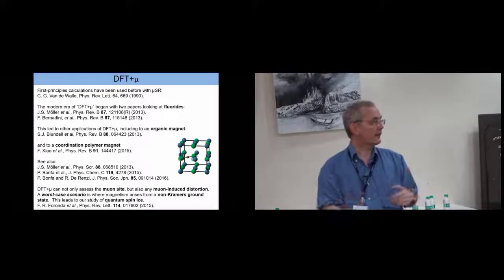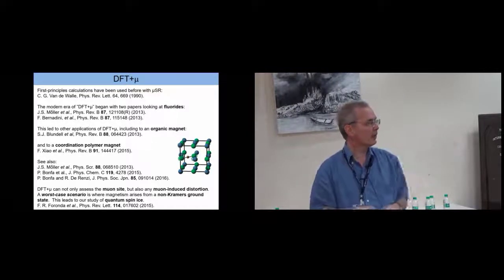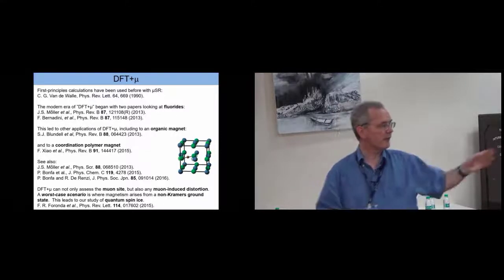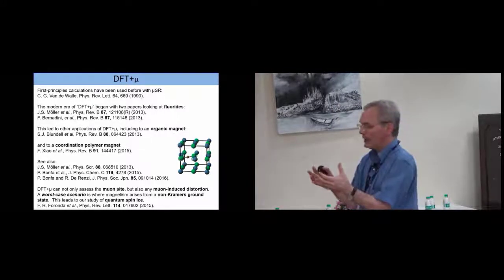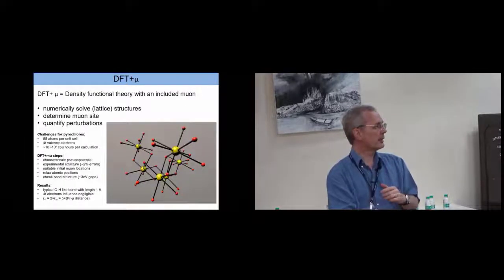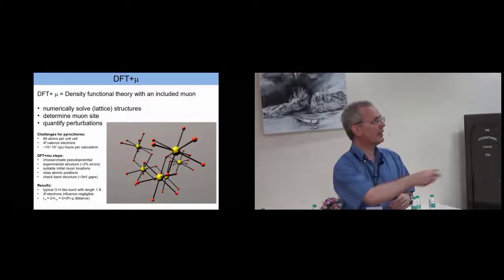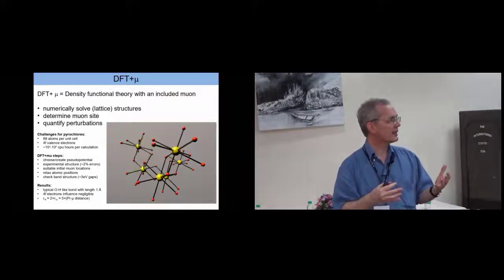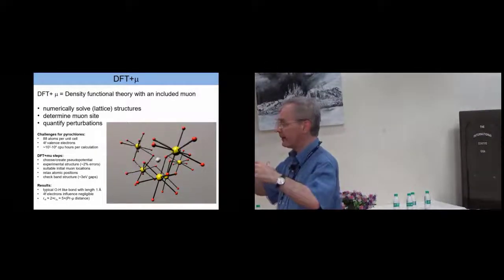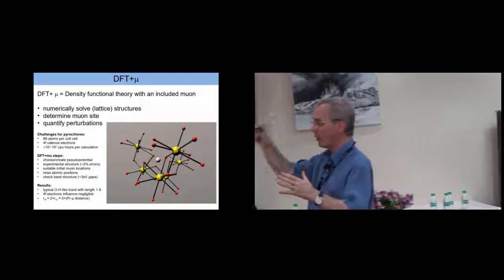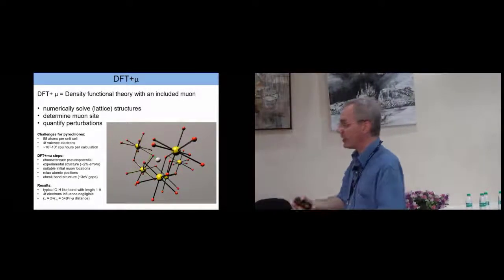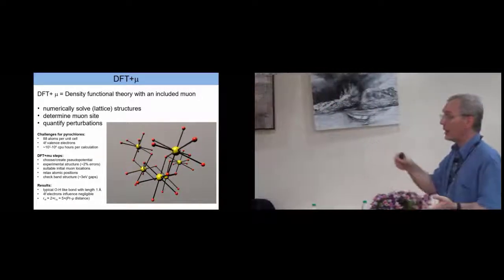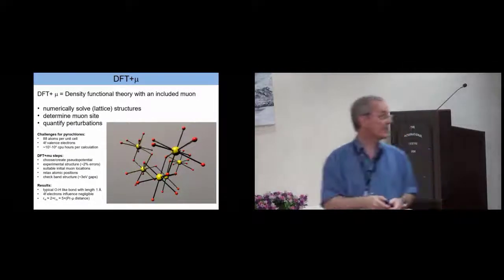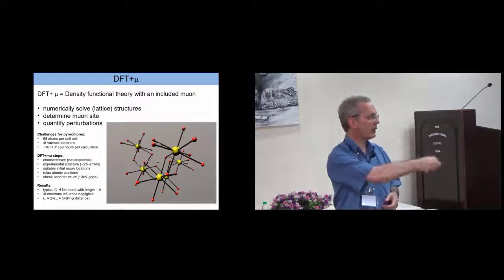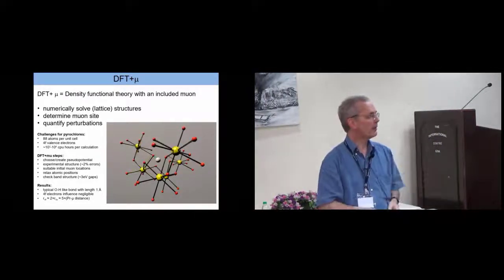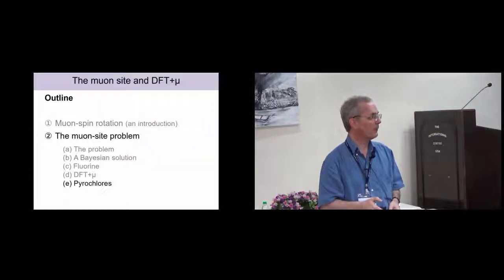And here is just a whole list of some references up to about 2016, there are many more since. What we essentially do is numerically solve the lattice structures to determine the muon site. We relax a lattice in DFT, we then add a muon at different starting positions and allow the structure to relax again, to find the lowest energy sites where the muon will sit. There are some details here for the calculations. I can talk about those more later, but I won't go on about that now.